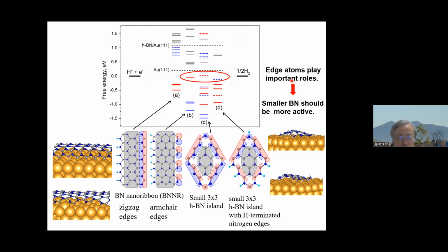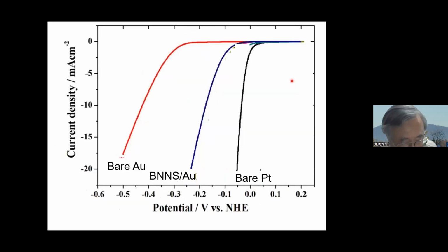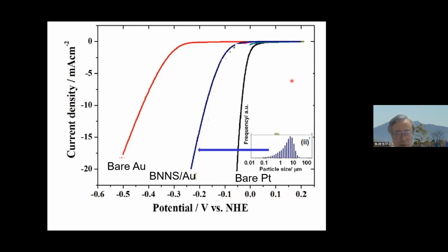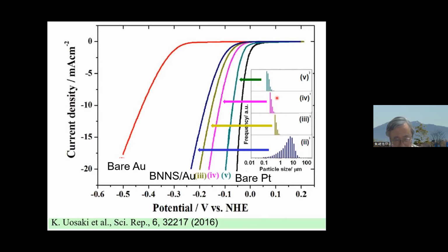So we then thought if edge atoms are important, smaller BN should be more active. So then we carried out the modification by size-selective boron nitride. This is the boron nitride nanosheet with this size distribution. Then we used a membrane filter to separate out these boron nitrides. By using this, the hydrogen evolution reaction is like this. As expected, the smaller the boron nitride nanosheet, the higher the activity. Actually, the highest activity is very close to platinum, only a 50 millivolt difference or something like that. So that is very good.